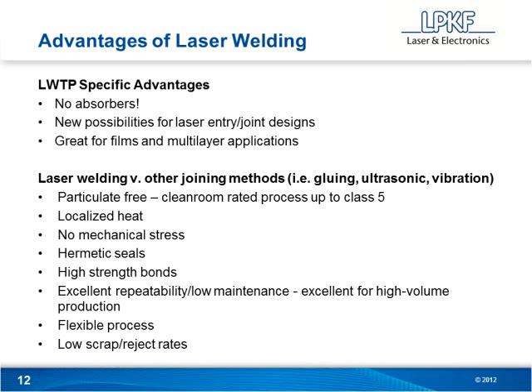If you're familiar with regular through transmission laser welding, commonly the lower layer had to be black or of a darker color. That would allow for the laser to be absorbed into that part. That being said, we don't have to have that anymore. Now we can weld 2 plastics without these absorbers. So this opens up possibilities for new joint designs, and also obviously for color combinations. Beyond that, we can do multi-layer applications with films. And it doesn't even have to be films. We've done hard to soft. We can do hard to soft to hard, and you'll see a few examples of that here in a minute.